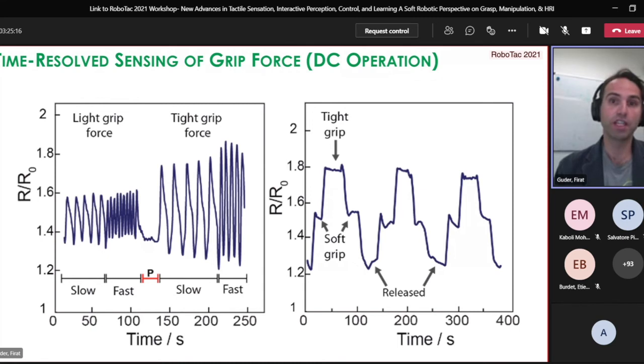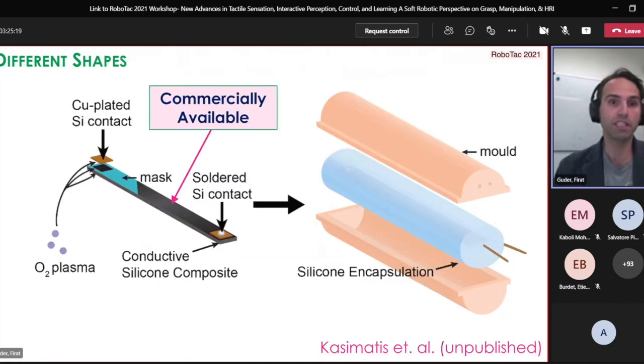But something really interesting happened not so long ago: we found out that there is a new manufacturer producing conductive silicone rubbers, so we were able to get some samples from them and try them out with our method, and it works beautifully as well. This way, we no longer need to synthesize our own rubbers, and we can just buy them from a commercial supplier. This is quite important for translation, because whoever is taking over this technology may not be a chemistry company, so they may not have the facilities to synthesize these materials.